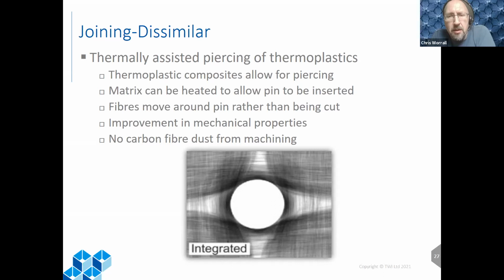So what we've looked at doing at TWI, starting about 8 to 10 years ago now, is making holes in composites without cutting fibers using a displacement technique. So this is mainly suitable for thermoplastic composites, where we can heat the thermoplastic matrix and then displace the fibers to the side to make a hole before cooling down the matrix, and ending up with something that looks very much like a tow steered or a tow sheared feature. But this can be made at any time after the part has been manufactured.